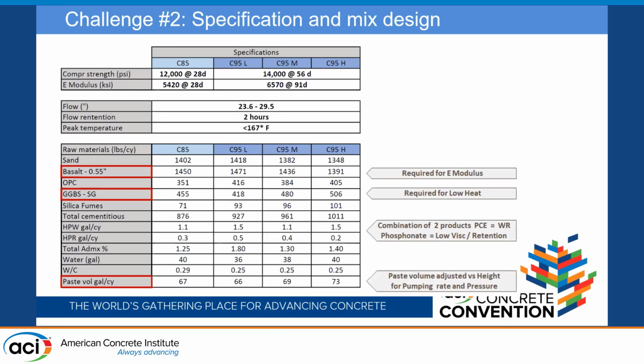The basalt aggregate helped us achieve modulus of elasticities in the 6,500 KSI range. And the basalt aggregates allowed the 14,000 PSI mix to save 14,000 tons of steel, thanks to the higher stiffness. It also allowed the design team to generate 21,000 extra square feet due to the section reduction of the superstructure walls. One of the key points about this is, if you remember, the basalt aggregate had to be shipped in from 125 miles away, a significant cost. That cost was about 2.8 million extra to bring that aggregate in. But the savings from the reduction in the steel and the increased space are on the order of 10 to 20 million.